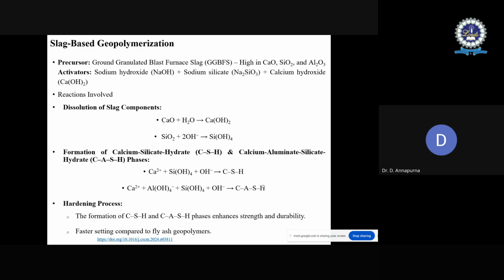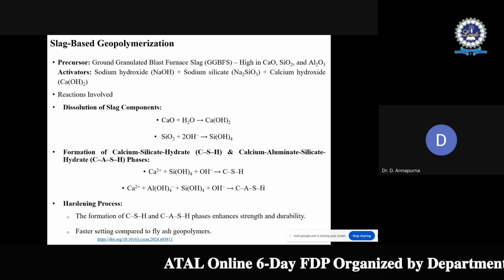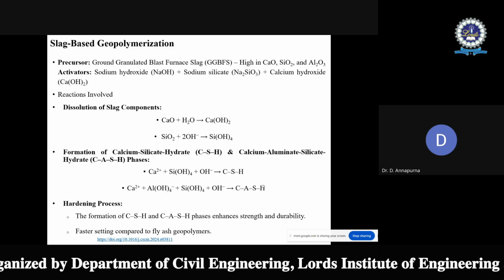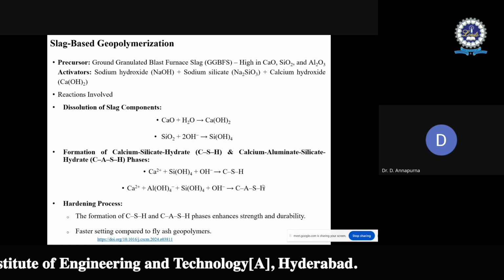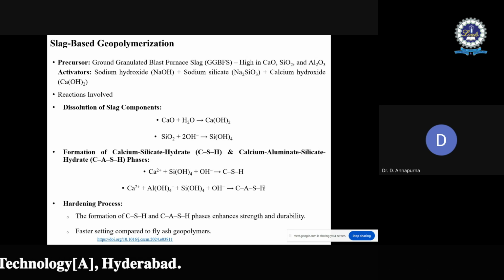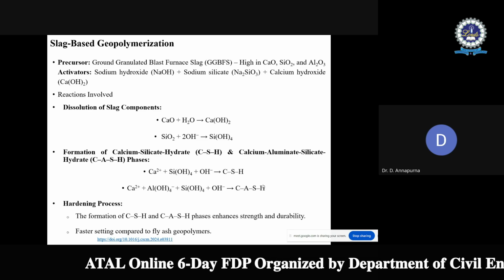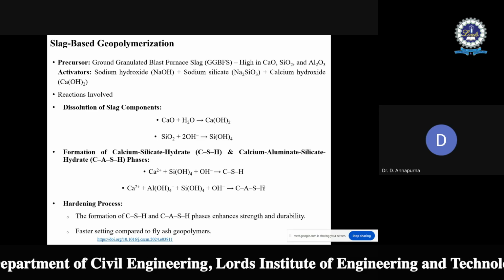When GGBS is added, it sets very fast compared with fly ash geopolymers. If you look at the literature, most of the geopolymer concrete produced using fly ash was done at Curtin University by a professor named Rangan BV. He conducted several experiments on fly ash based geopolymer concrete, because the fly ash reaction rate is low. So the geopolymer concrete was prepared using heat curing conditions.